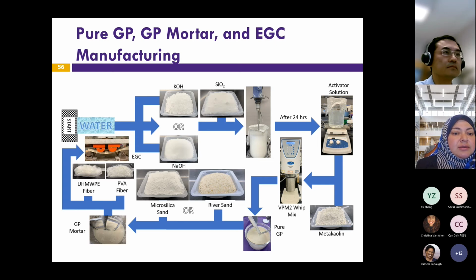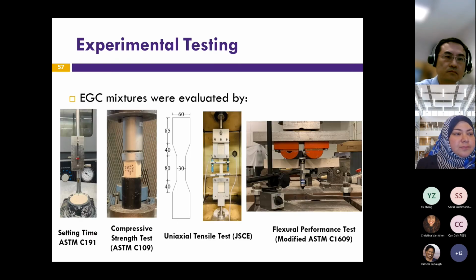Then we add the sand, whether it's river sand or microsilica sand. That gives us the geopolymer mortar, and then it's placed in molds and left to cure for 7 days in sealed conditions. So we usually strip the forms after 7 days, and we test it after 21 days instead of 28 in the case of regular concrete. Okay, and these are the tests that we experimented with. So we tested setting time, compressive strength, uniaxial tensile test, and flexural test.